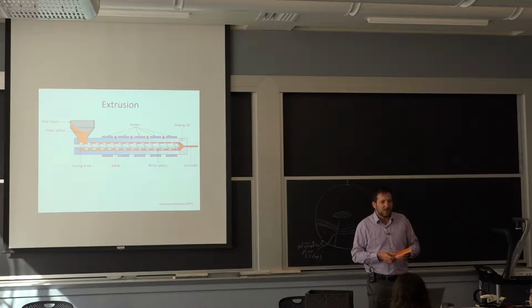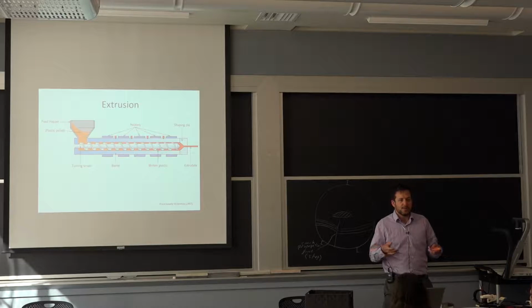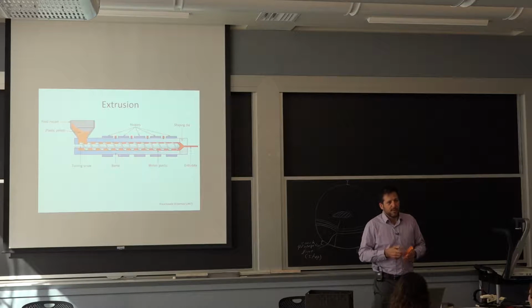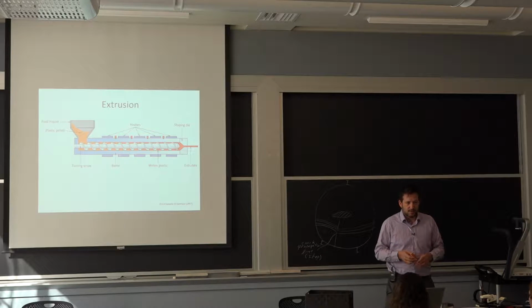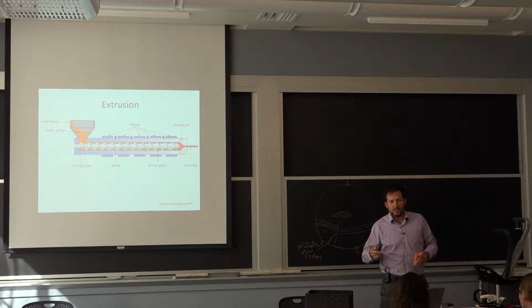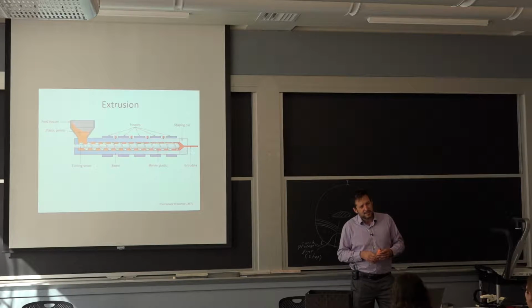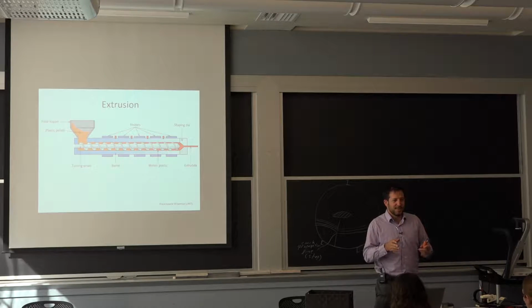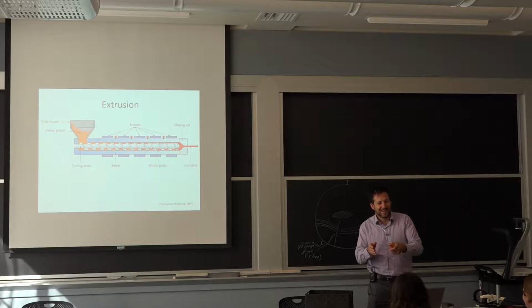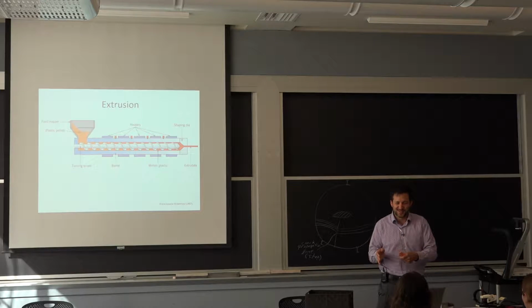Yeah, so the 10,000 hour test, you don't need a huge enclosure because then you're doing it at 400 psi and with water. So it's not a big deal then. Yes. Now, but the fittings for this is small, but if you look at big drainage fittings, they can be tested in a range of 2,000 to 3,000 psi. And then they'll fail in service at 200. How long is 10,000 hours? About 14 months. Yeah. And then, so you learn something after about 14 months. It's not necessarily the answer you want. So there's a lot of iterations in that process.